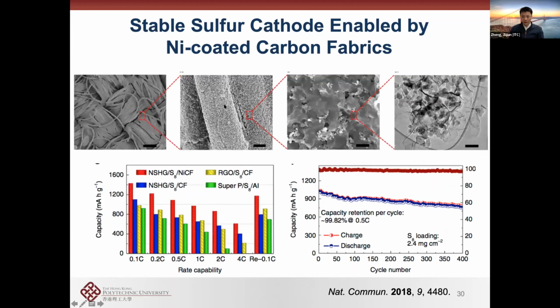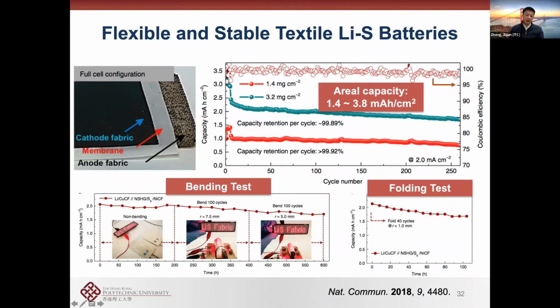Okay, and this is the cathode side. We can also do the same trick to load the sulfur very uniformly on every single fiber and enable this high rate and high stability performance. I'll skip this part. Basically, if you pair this cathode with the anode together with a separator, then we can come up with a very high energy density lithium sulfur battery. At the same time, they are very flexible. We can even fold it, and the device doesn't really fail. There is some deterioration of the capacity, but they don't fail immediately.